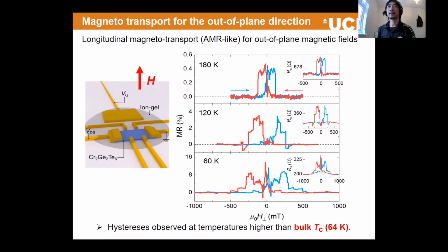This is just a measurement of magneto transport as a function of this applied magnetic field. So just moving back and forth of magnetic field and see how resistance changes. The only thing that we want to know is, although this is a really jumpy behavior, which depends on the domain wall propagation and nucleation, which is very complex, so I don't want to talk in great detail here, but hysteresis is sustained up to 180 Kelvin. And against the bulk Curie temperature is 64 Kelvin.